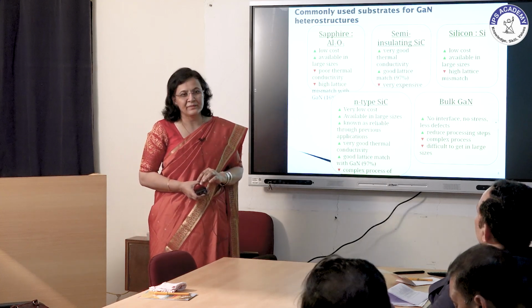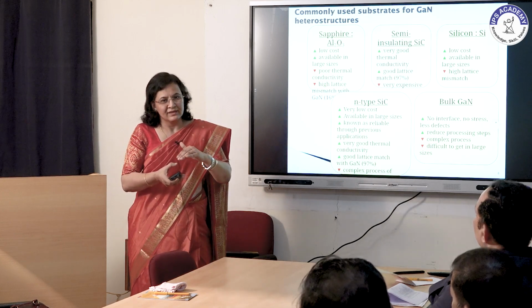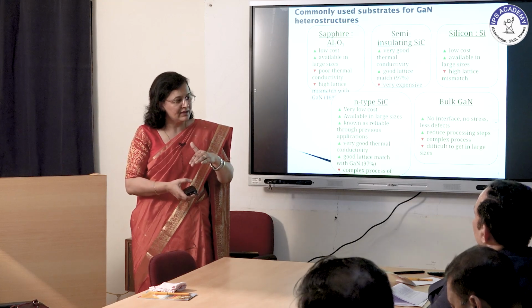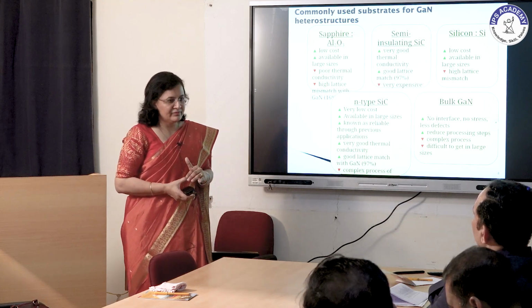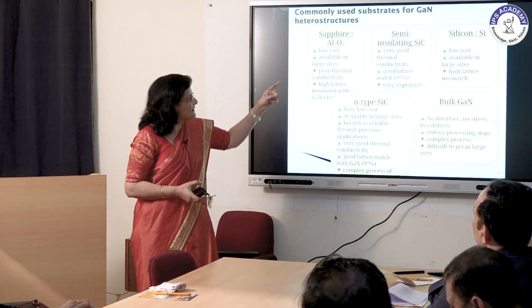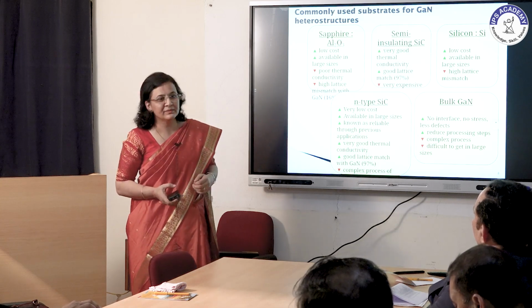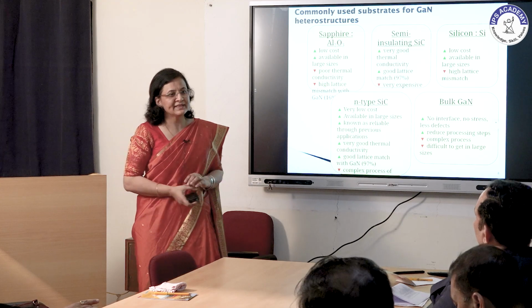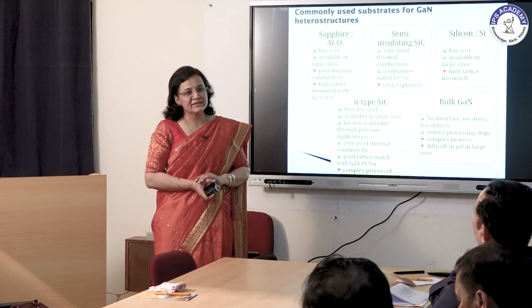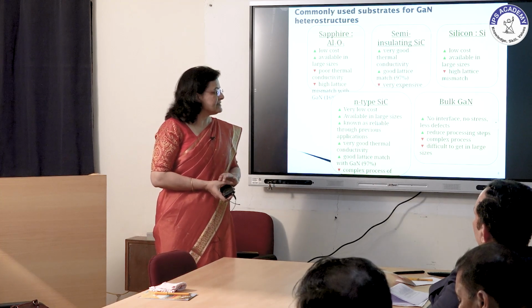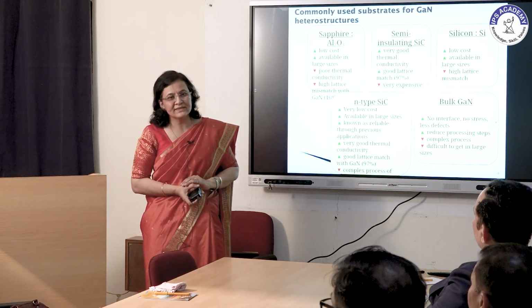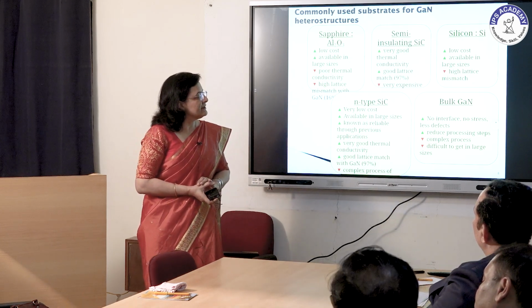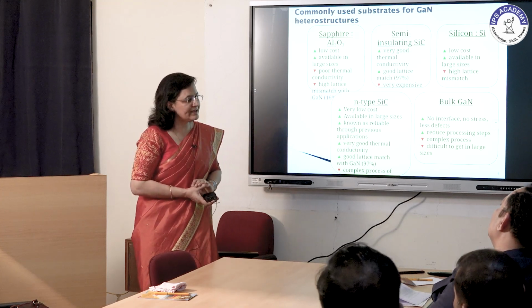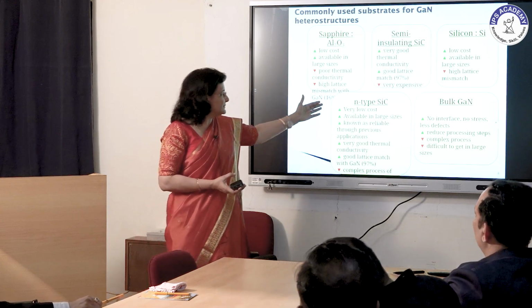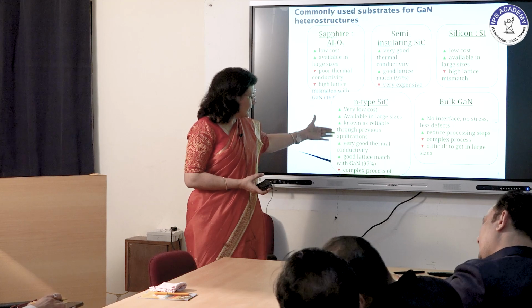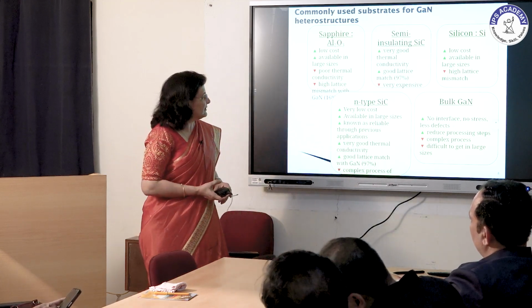High lattice mismatch with gallium nitride is also an issue. If lattice mismatch increases and you have big structures made one on another, it can fracture and your whole device can stop functioning properly. So lattice mismatch is a problem. Semi-insulating silicon carbide has very good thermal conductivity and good lattice match, but it is very expensive. Silicon based structures are also available with gallium nitride, but again there is high lattice mismatch, but the technology is stable, and we have many devices. The silicon industry is quite stable. N-type silicon carbide, that was semi-insulating, this is N-type. All things are good, but the complex fabrication process is a disadvantage.